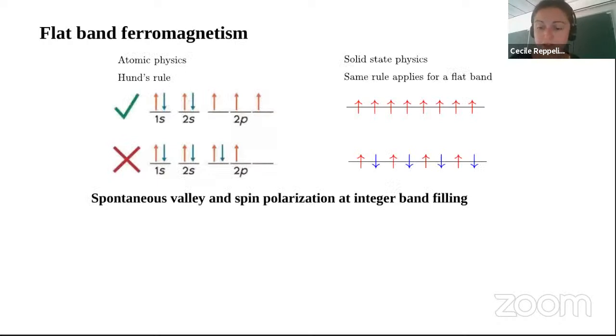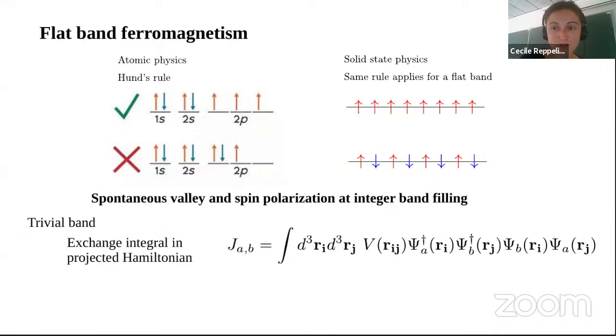This is a phenomenon that's often called flat band ferromagnetism, and it can be linked to Hund's rule in atomic physics. Hund's rule tells you that when you have atomic orbitals that are degenerate, it's energetically more favorable to fully fill one level with electrons of the same spin rather than having electrons with opposite spins. So it's basically the solid state equivalent of this rule that is observed in magic angle twisted bilayer graphene, and which shows up through a valley spin polarization at integer band filling. Well, at least that's what you expect from Hund's rule.